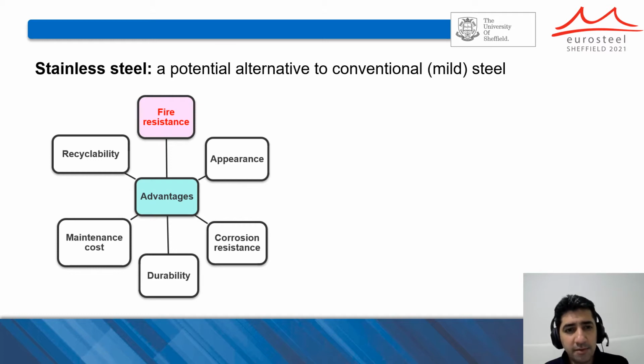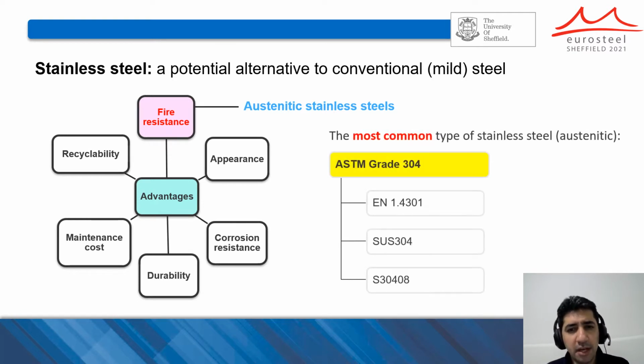An improved fire resistance is specifically observed in austenitic stainless steels with a nickel-based structure. The most common type of austenitic stainless steel used worldwide is ASTM grade 304 and its equivalent grades, as you can see in the figure.